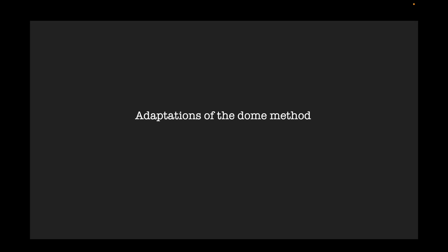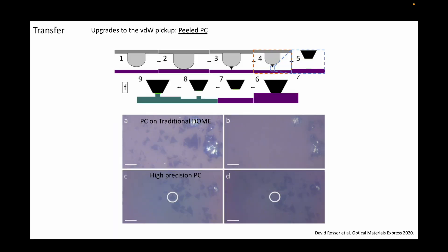There are several adaptations of this PDMS dome technique. I will go over three of those now. First method is shown in this work, where they utilize the fact that PC has a poor adhesion to PDMS. They take advantage of the microtenting effect arising from the PC being peeled away from the underlying PDMS, and use this as a fine tip to pick up a flake that is in a densely packed area.